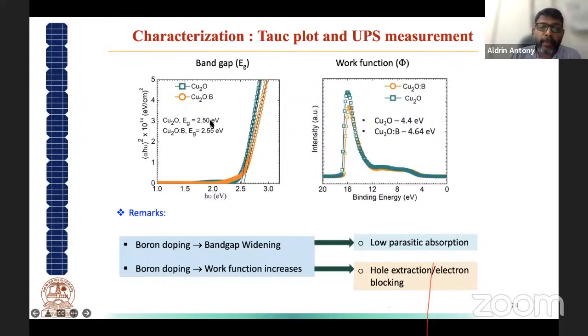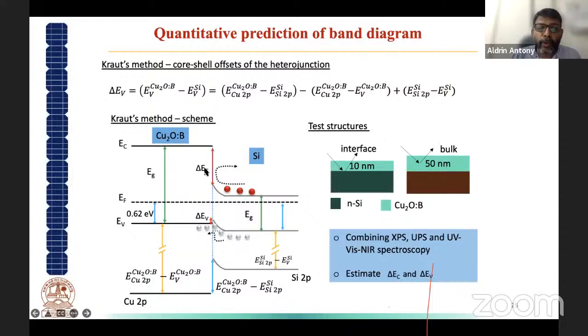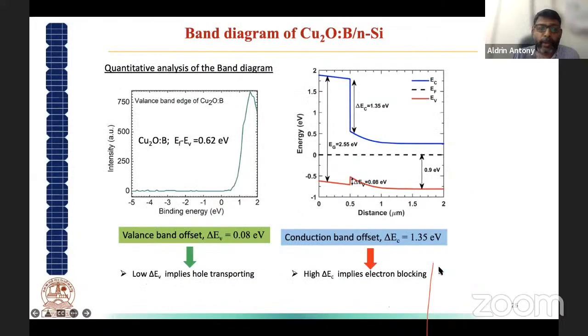And once we have this band gap and the work function, and then you could find from UPS, that's ultraviolet photoelectron spectroscopy, you could also calculate what will be the delta EV value or delta band offsets. So from that, you could create a band structure. So we created the band structure of a copper boron oxide with the silicon, and this is the silicon you can have, and this is a copper boron oxide.